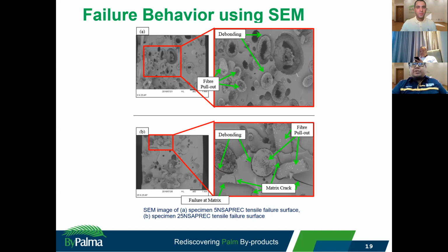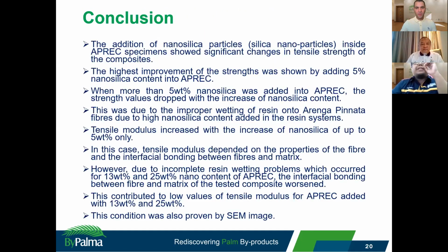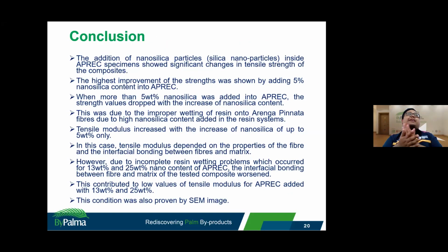So actually, I want to show you that the addition of more than 5 weight percent nano for this project will reduce the properties. As for the conclusion, if you want to add more nanosilica content inside this Arenga Pinnata epoxy composite, maybe we should try a different method, such as vacuum bagging, so that the higher viscosity epoxy embedded with nanosilica can flow inside and bond with the Arenga Pinnata. That's the conclusion that I made.